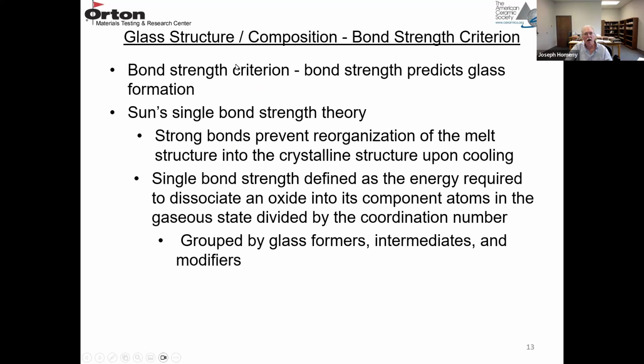The other common theory is the bond strength criterion. And this is based on bond strength, and that's used to predict glass formation. Sun developed this single bond strength theory. Basically, he's saying that if you have very strong bonds, that prevents the reorganization of the melt structure into a crystalline structure as you cool that melt. So strong bonds prevent the reorganization.